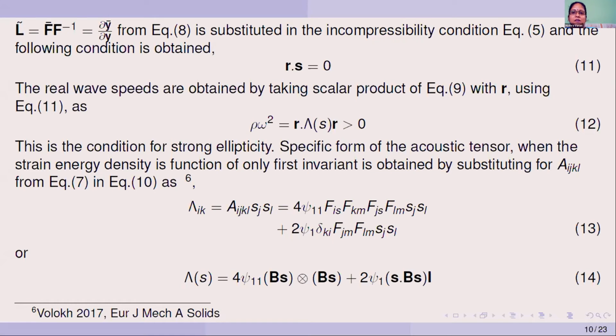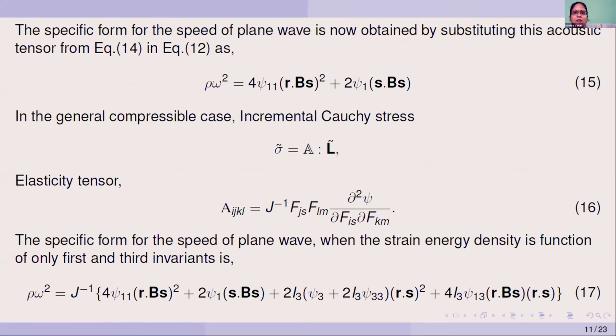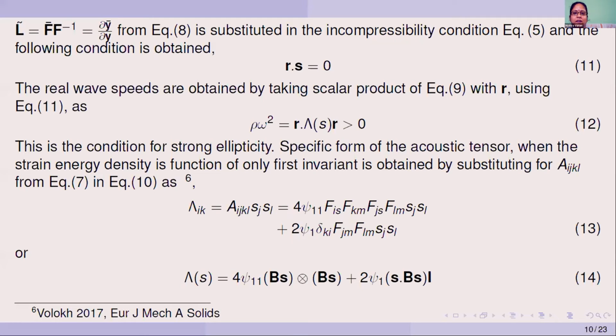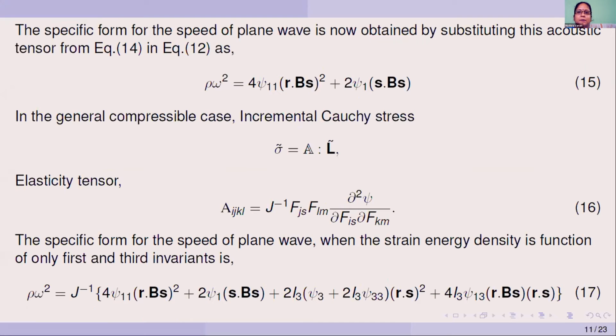So when the specific form of this strain energy psi is a function of only the first strain invariant, we already calculated the incremental form of this elasticity tensor, which we plug into this acoustic tensor to obtain its incremental form. And this is the tensorial form for the acoustic tensor. Now we substitute this acoustic tensor back into equation 12, which is this condition of strong ellipticity, and we obtain this specific form for the speed of plane wave.